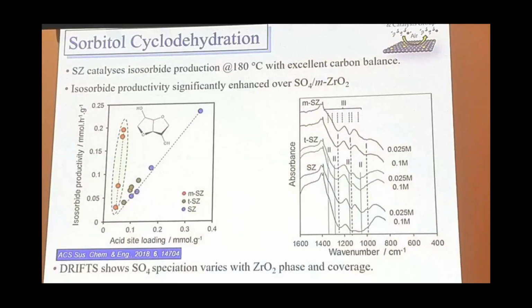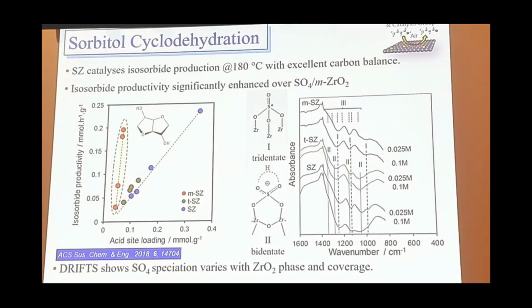So we've looked at this with infrared, and it's quite a complex region for the sulfate bands. But essentially, when you look at the tetragonal phase, you have two components which are based around the tridentate species, which are labeled 1, and the bidentate species, which are labeled 2, that are sort of overlapping in the spectrum.